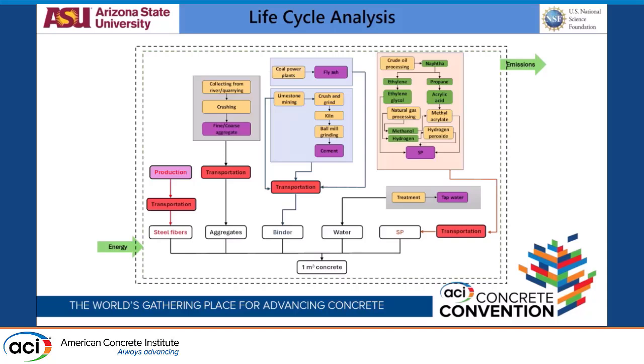So why did we now get the increase in the strength? Why not use UHPC mixes? What is the detriment in using systems like this? Why are we not going for it? To see that, we need a proper life cycle analysis of these mixes. So for the L30 mix that I talked about before, that's basically 30% limestone, 70% cement, 50-50 binder and aggregate. For that mix, which is a normal strength, and the UHPC mix, we did a life cycle analysis from cradle to gate, basically from initiation to the mix phase.